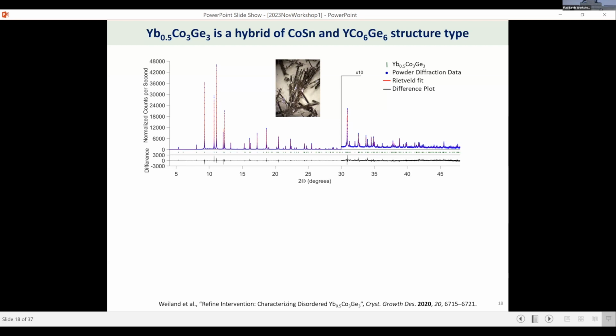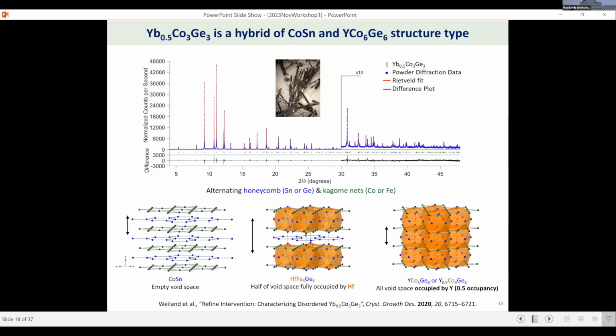And so we thought that it is important for us to really confirm our structure determination. We got nice crystals, but telling our students to grind those crystals up, oh dear. But you know what? We have to have complementary confirmation of what we think we got. And it turns out that if you look at the cobalt tin, which is a known phase, we will hear more about it at this meeting.